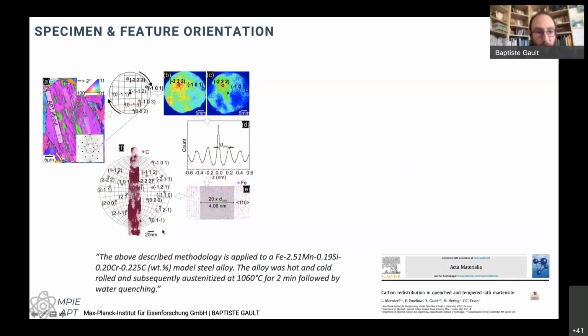This can be very useful sometimes when we want to look at, for example, this martensitic steel, where we did EBSD beforehand. We lifted out from a specific grain, knowing that the 111 direction would be quite close to the main axis of the needle. So when we then do the experiments, we have the 111 direction very close to the center of the detector. So the 111 set of planes will be very close to the center of the detector.